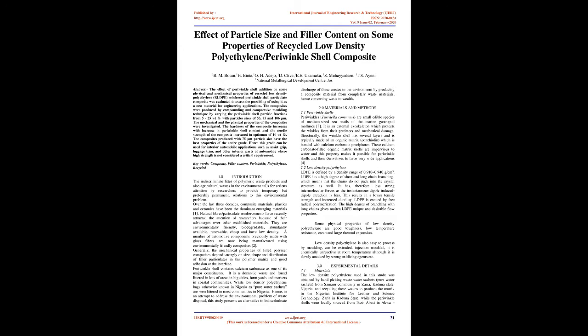5-25 wt% with particle sizes of 53, 75, and 106 µm. The mechanical and the physical properties of the composites were investigated. The hardness of the composite increases with increase in periwinkle shell content, and the tensile strength of the composite increased to an optimum of 10 wt%. The composites produced with 75 µm particle size have the best properties of the entire grade.